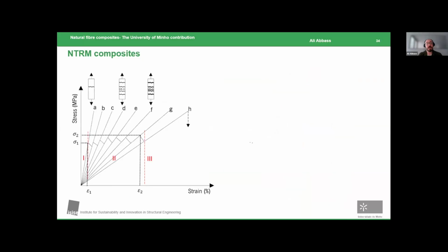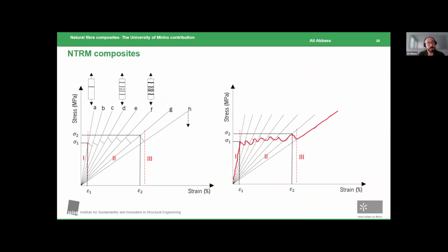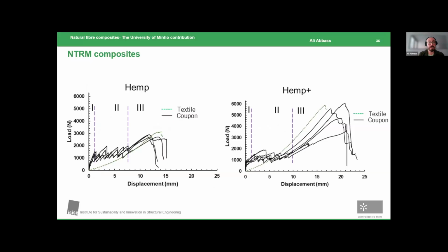materials. So for a composite material to behave properly, first, it should show three distinctive phases. The first phase, you would see it here, is dictated by the mechanical properties of the matrix itself. So we apply tensile load, then we reach the tensile strength of the mortar. Then we have failure, and then the fibers in a good composite material, well designed, should accommodate these fibers to the next intact phase of the matrix, and go on, showing at the end these three distinctive phases, as you can see here.